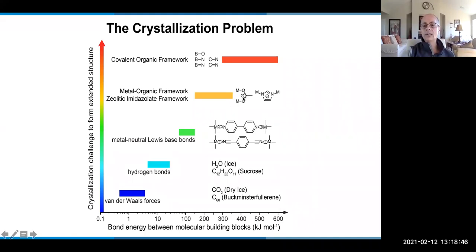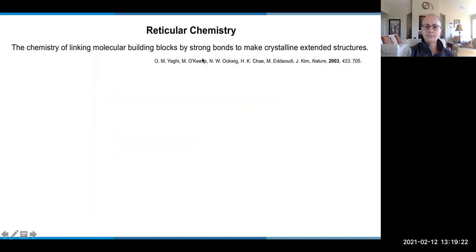Now, as your linkers or the organic ligands have charges, and you're linking them with metal ions, the charge interaction increases this bonding strength and the difficulty in crystallizing these materials. So what we've done over the years is we have overcome this crystallization challenge. We have figured out ways of balancing the kinetics and the thermodynamics of the system so that we can crystallize MOFs and the subject of today's lecture, COFs, molecules linked together by covalent bonds.